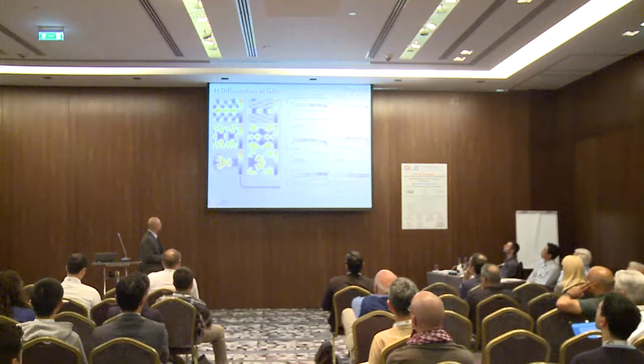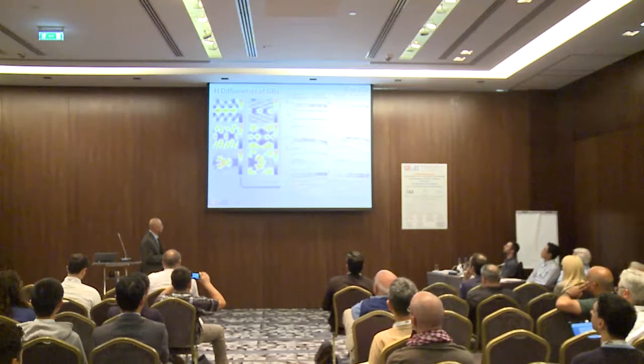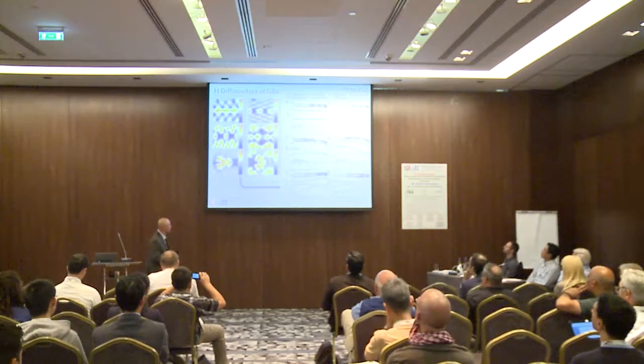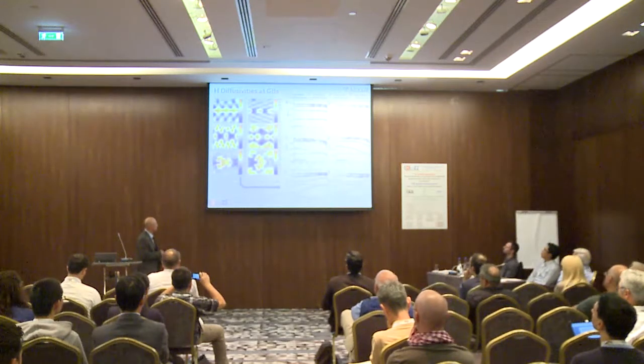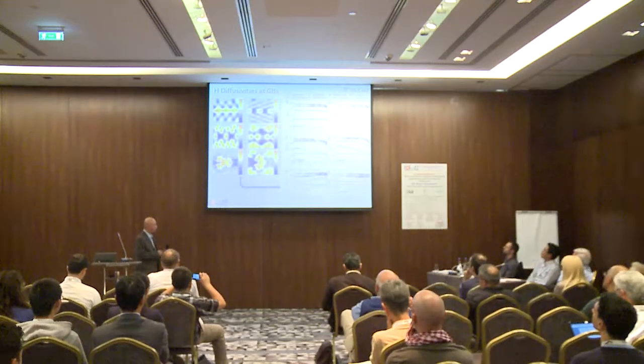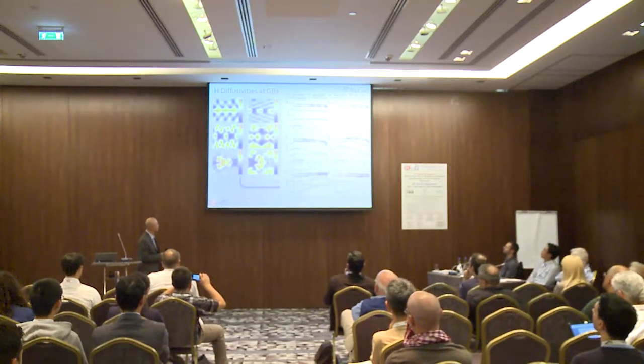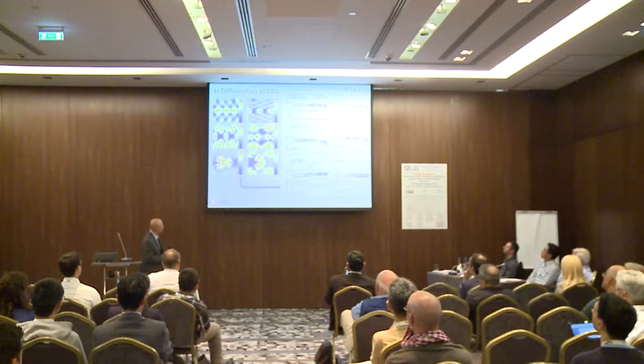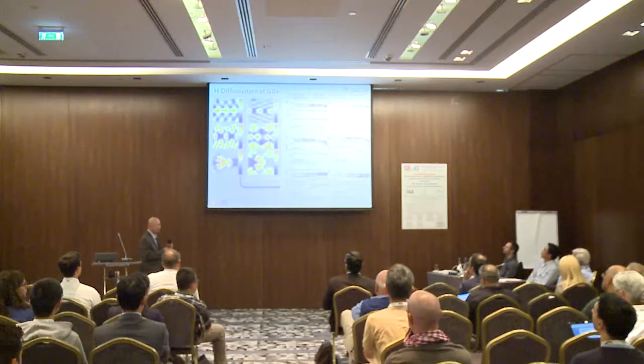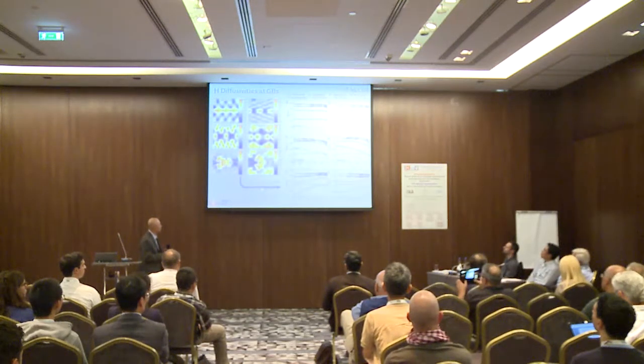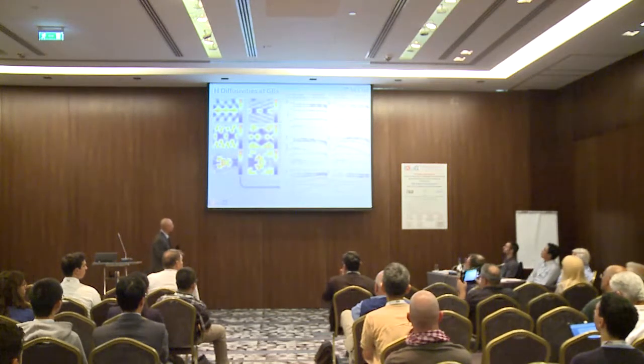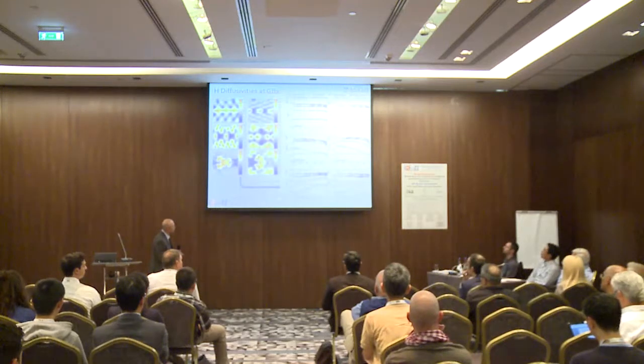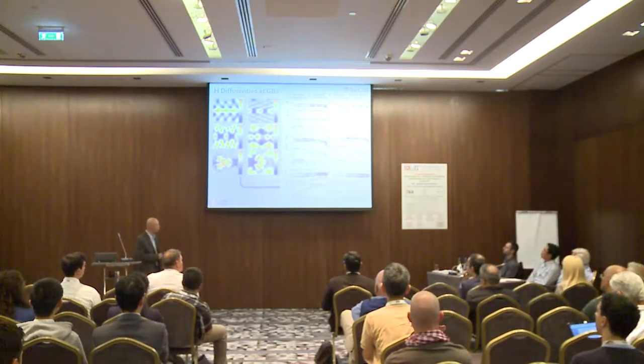It turns out that those kinetic Monte Carlo simulation results can also be well represented by an analytical formula. If you know the effective barrier, not individual barriers, and you know the energetics, this formula takes into account not just the barrier, but also the energetics of hydrogen at the grain boundary. Then you can actually predict the kinetic Monte Carlo simulation results.